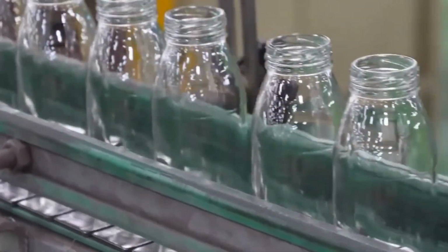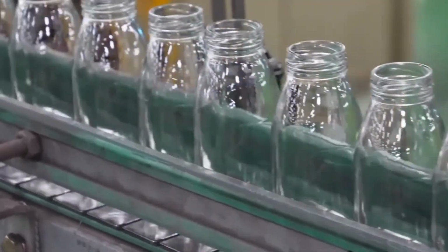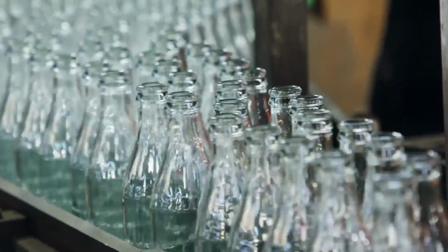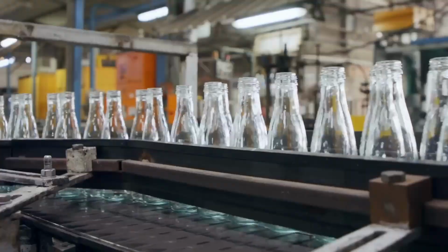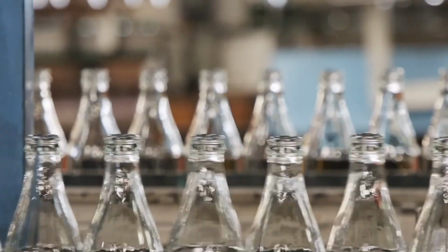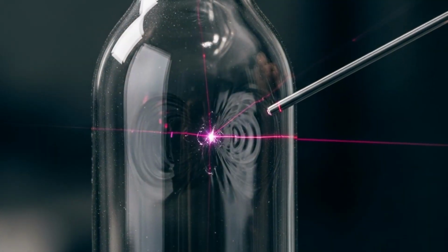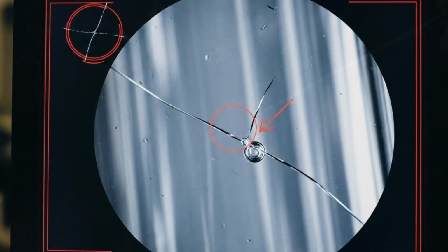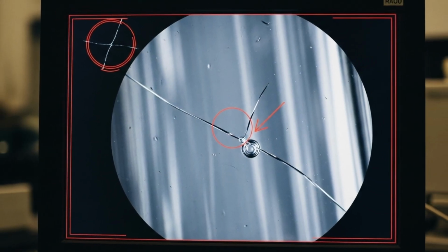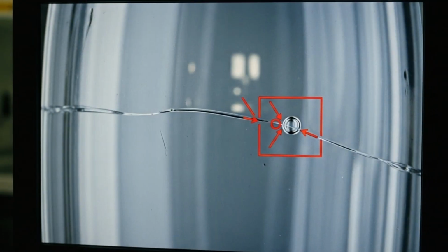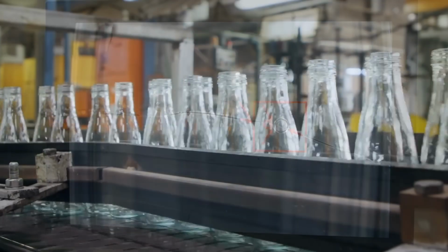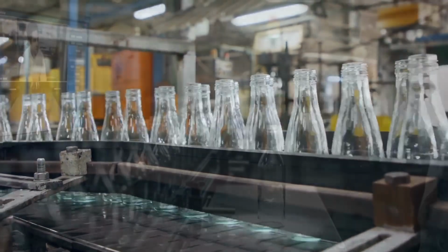High-speed cameras, capable of capturing thousands of images per second, scan each piece in 360 degrees, detecting flaws almost invisible to the naked eye. Microscopic cracks, trapped bubbles, or variations in thickness. Even an imperfection, just a few microns wide, can weaken the glass. Artificial intelligence systems analyze those images and classify each defect instantly.